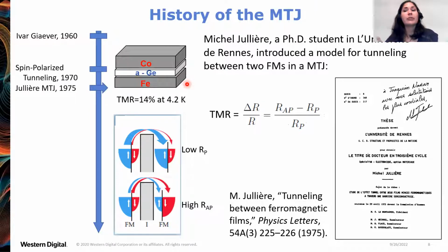So he had learned from Meservey and Tedrow that spin is conserved in the tunneling process, and therefore there should be two well-defined resistance states. When the two ferromagnets have their magnetization oriented parallel to each other, you have a lot of spin up electrons at the Fermi level in one ferromagnet, and a lot of empty spin up electron states for them to tunnel into in the other ferromagnet. And this leads to a high tunnel current and correspondingly a low resistance state. But when the two ferromagnets have their magnetization oriented anti-parallel to each other, there's this mismatch of the density of states, and thus this leads to a low tunnel current and correspondingly a high resistance state.